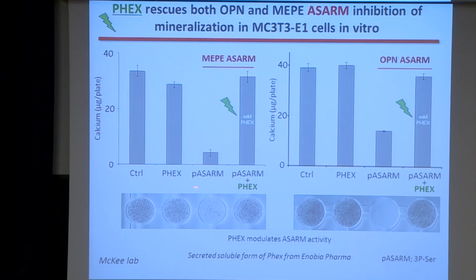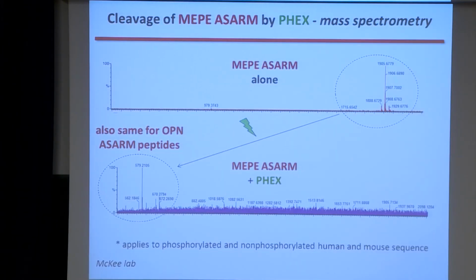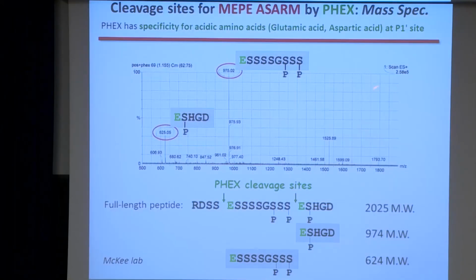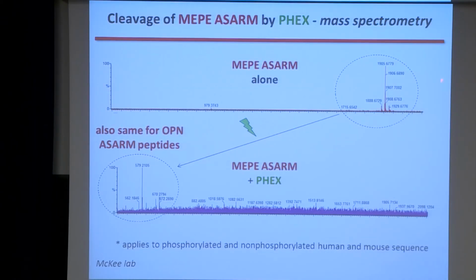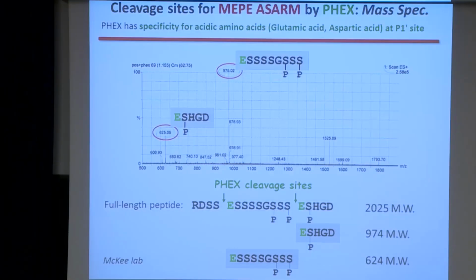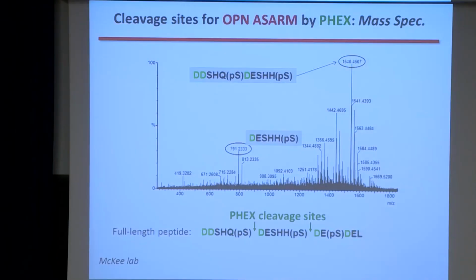We could degrade, it seemed, the inhibitor for both the MEPE-ASARM peptide and the osteopontin peptide. And with mass spec, we were able to notice a complete degradation from here to here. This is how you show substrates by mass spec. PHEX was degrading MEPE-ASARM, and we were able to map the exact cleavage sites within that ASARM peptide. So this fit with the XLH story in the patients.